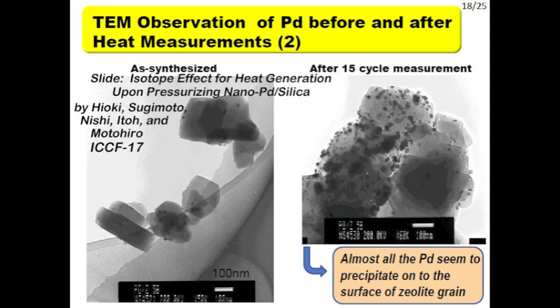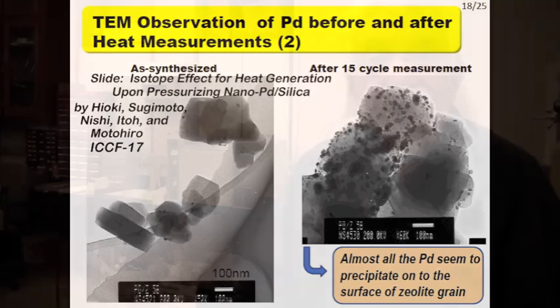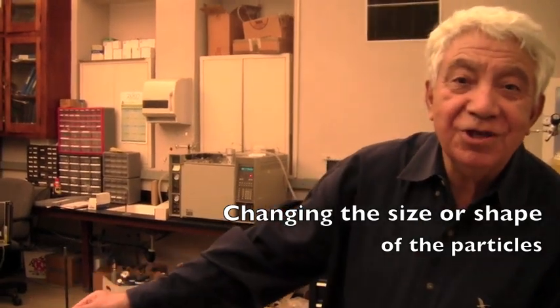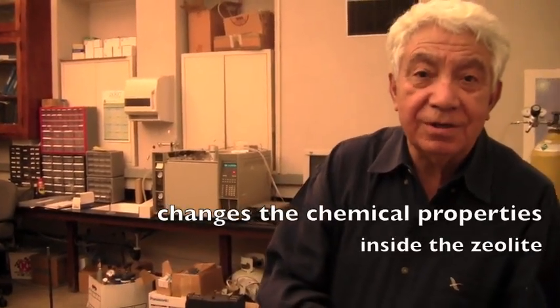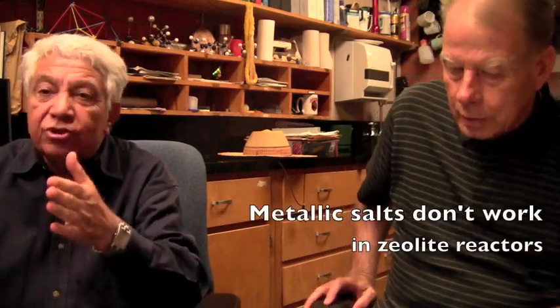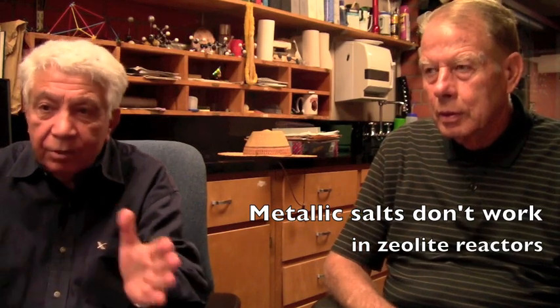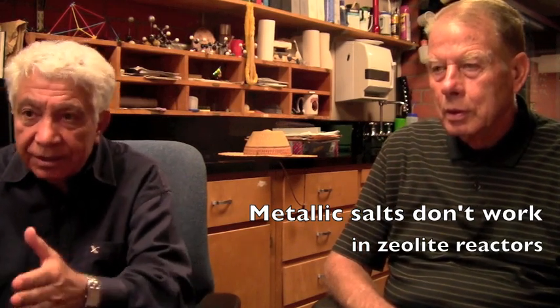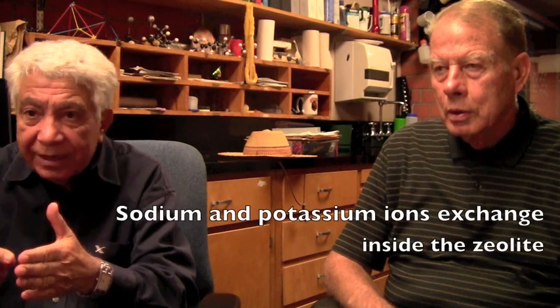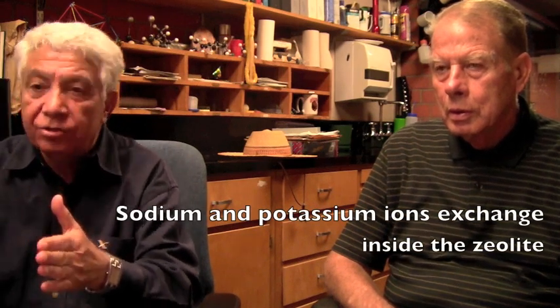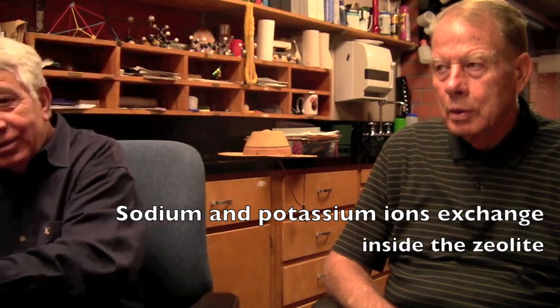The people that said, oh, we made the nanoparticle. What size? What shape? Because if you change those, the chemical reaction changes. Perhaps this changes as well. But the problem is you cannot use a salt of a metal, doesn't matter whatever it is, palladium, nickel, and say that I put this inside. Because as soon as you put this, sodium or potassium exchange. It means they go away and the other one comes.